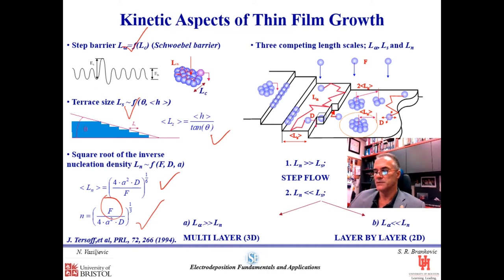However, if the opposite is true, then we can have a relation where L sub alpha is much larger than L sub n, which means that the probability for nucleation on top of the cluster is much larger than the probability for the adatom to step down and incorporate in the growing layer, which typically results in a pyramidal, rough 3D growth. In the opposite case, when L sub alpha is much smaller than L sub n, all adatoms that land on top of the clusters will diffuse and incorporate in the growing layer, and we will have a 2D growth.